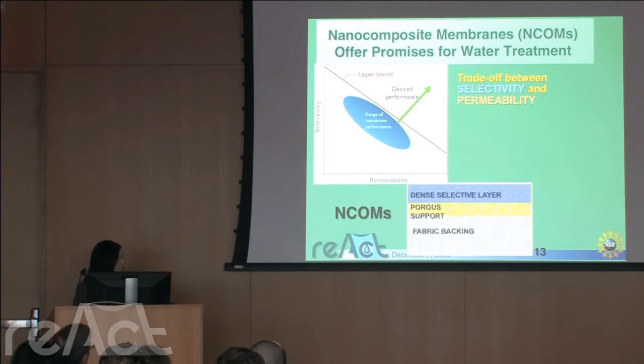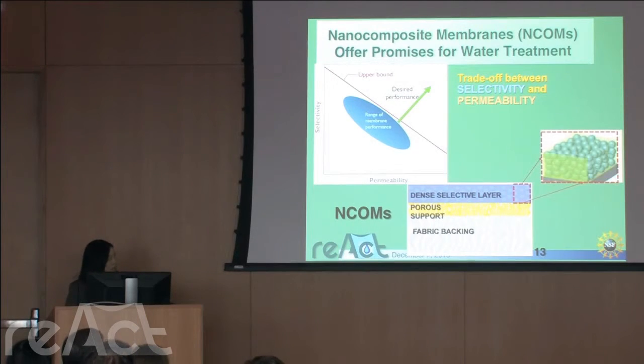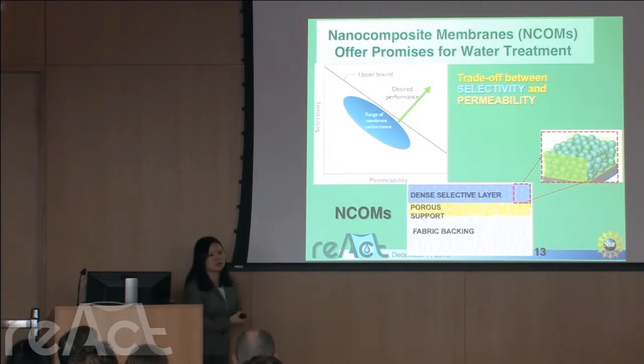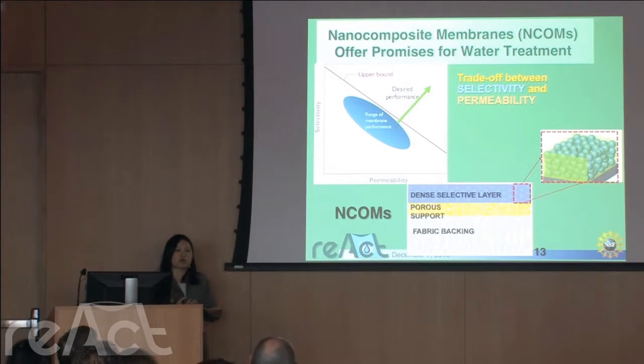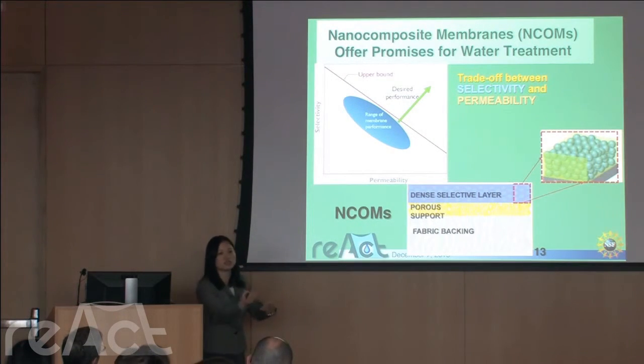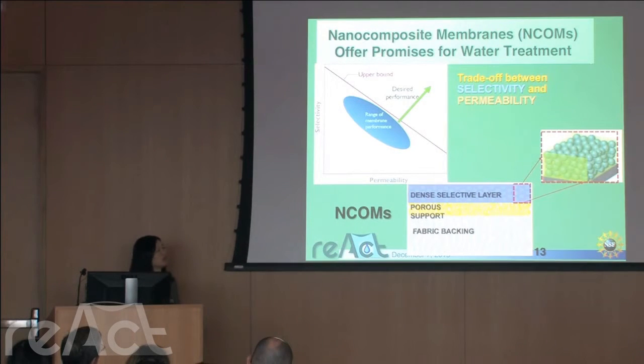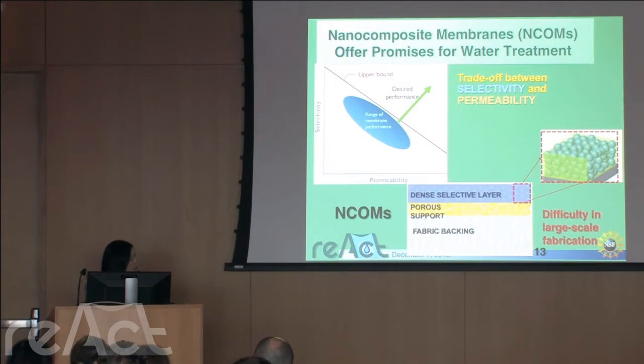So the question is, how do we do this, right? We came up with this idea. This is De-Jong Lee, and the question is, how do we generate nanocomposites? Can we have a porous support and introduce a dense selective layer? One of the ideas, of course, is going back to using nanoparticles. If we introduce nanoparticles into this nanoporous membrane, can we enhance the mechanical stability? Because even though the nanoparticles contact each other, it's very easy to take them off. So how do we enhance the mechanical strength? Can we use polymer? And if we use polymer, how do we make it more interesting, right?